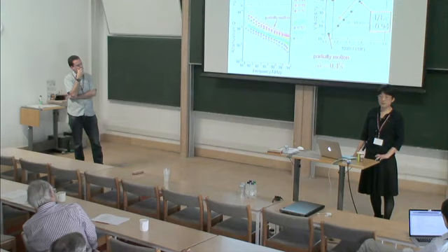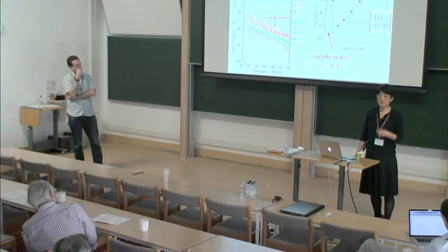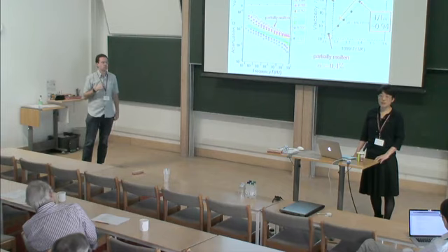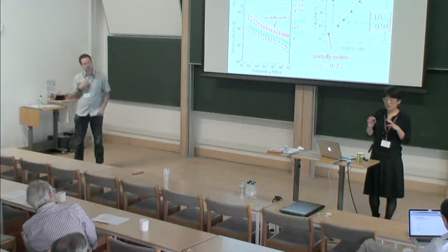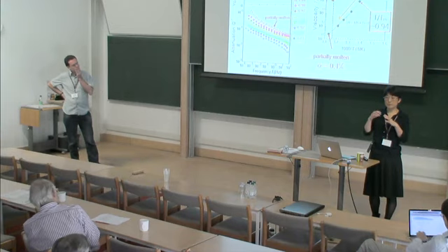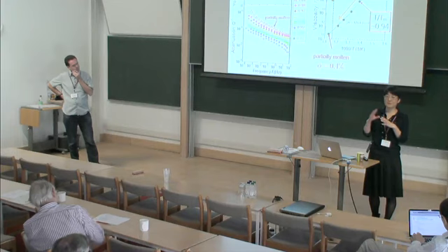So this effect very strongly affects shear wave but not so much P wave. So a high VP/VS ratio might be explained. If we do not assume equilibrium shape of melt for melt geometry, the VP/VS ratio is not so high.